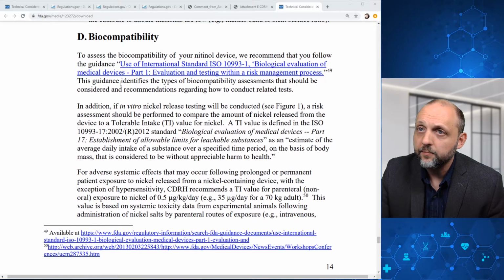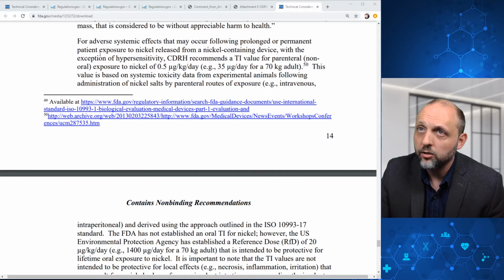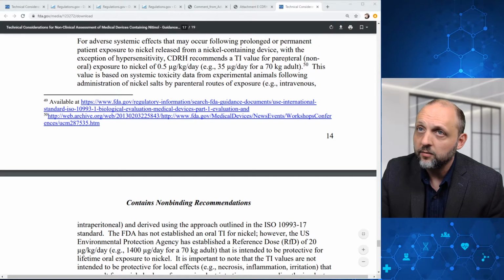And then in terms of biocompatibility, FDA references the biocompatibility biological evaluation guidance in terms of ISO 10993-1. And in addition, if in vitro nickel release testing will be conducted, a risk assessment should be performed to compare the amount of nickel released from the device to a tolerable intake value for nickel. For adverse systemic effects that may occur following prolonged or permanent patient exposure to nickel released from a nickel-containing device, with the exception of hypersensitivity, CDRH recommends a TI value for parenteral exposure to nickel, and this value is based on systemic toxicity data from experimental animals following administration of nickel salts by parenteral routes of exposure. Here's some values that they're recommending.